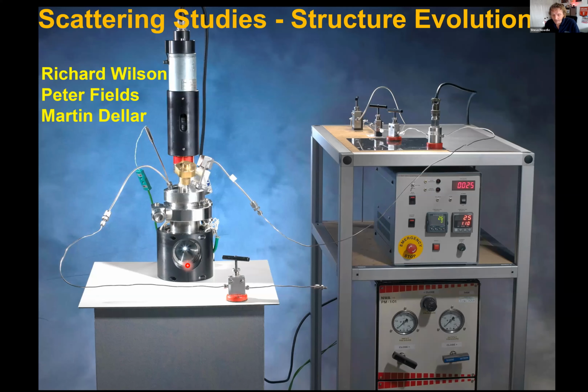It turns out that the best way of doing this is to create windows out of diamond. Diamond is strong enough, and we could also have windows that were just a few millimeters thick and would be able to hold back the high pressure. And it worked beautifully. The diamonds weren't that expensive - they're industrial grade diamonds, not the ones you might buy as jewelry. And it worked really well.